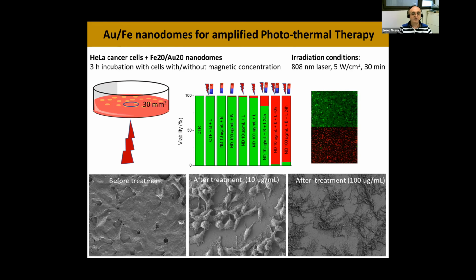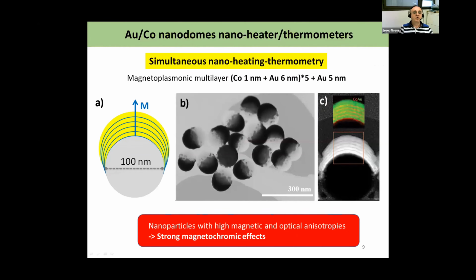So this brings us about what is the actual temperature in the liquid surrounding the particle. We need to do that to be able to tune the conditions for the optimal killing of the cells using only apoptosis and not necrosis. So then it brought us, can we measure locally the temperature of the nanoparticles, all the liquids surrounding the nanoparticles?